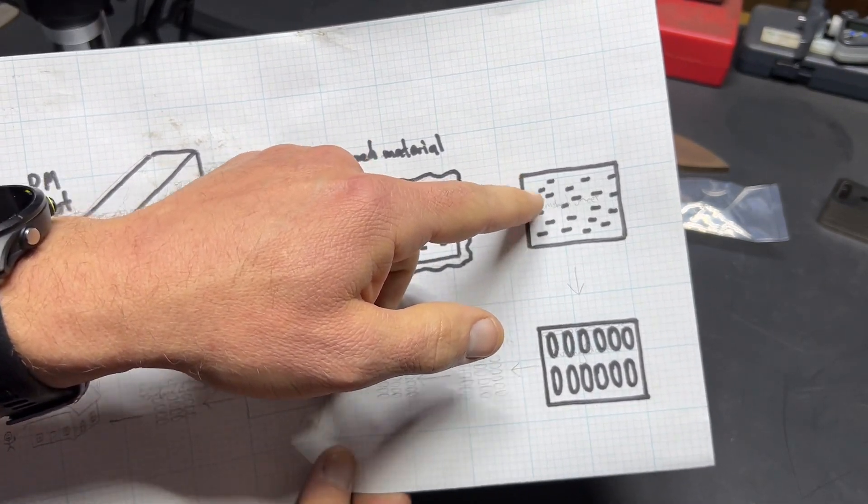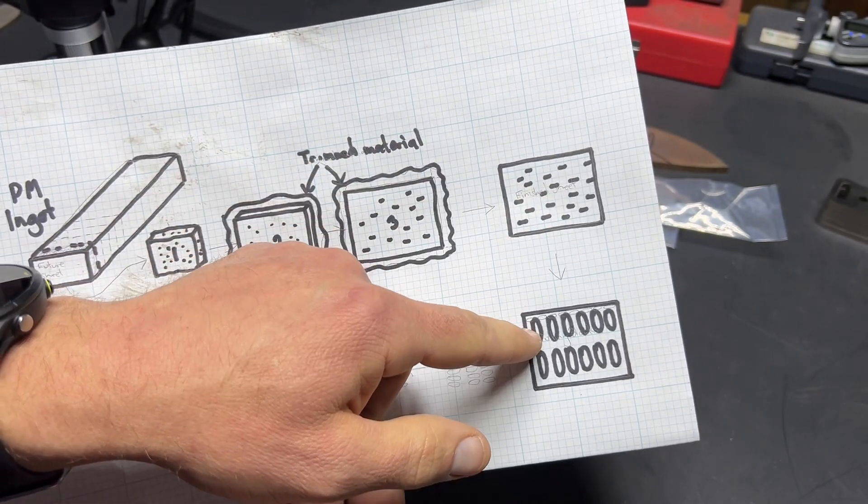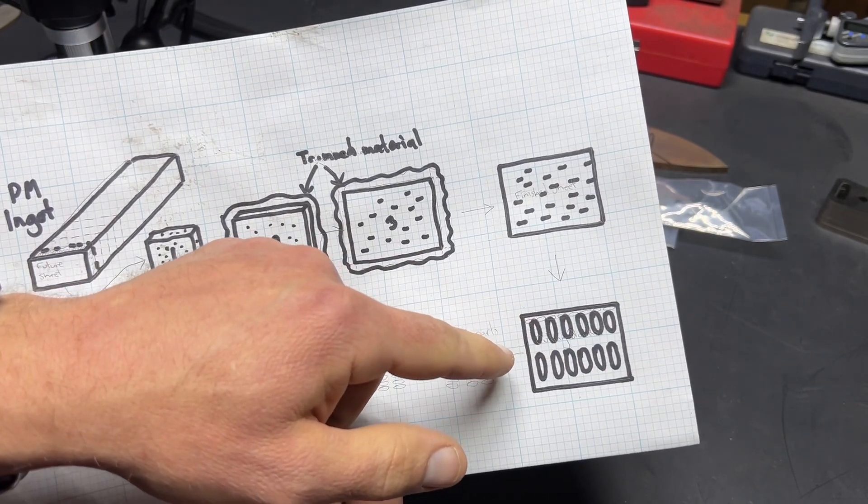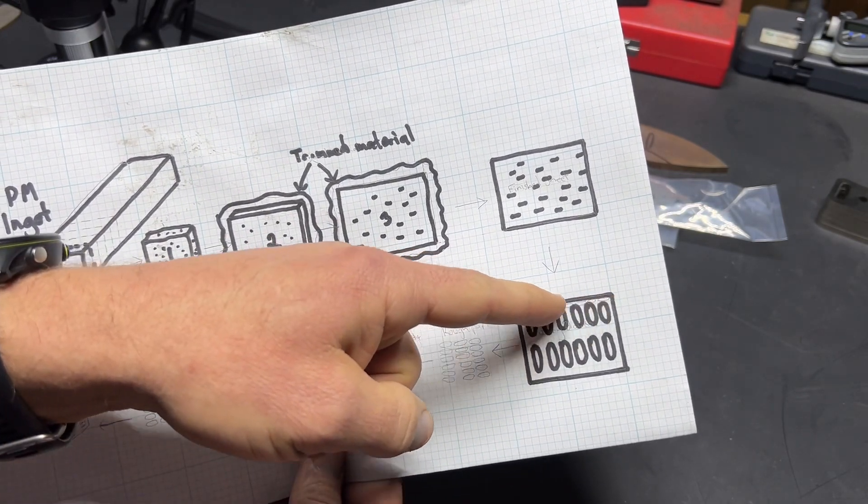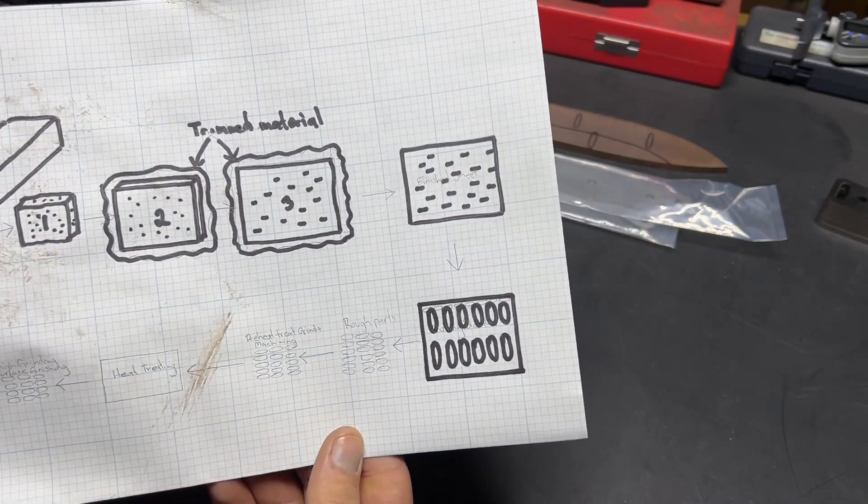How these manifest is going to depend on how you cut your parts out of the sheet. But what I think is occurring in here is you have these long stringers of voids inside these sheets. With the 5.1s we cut in this orientation because it was the most efficient nest, so they're coming across the parts in a perpendicular way to the length of the part.